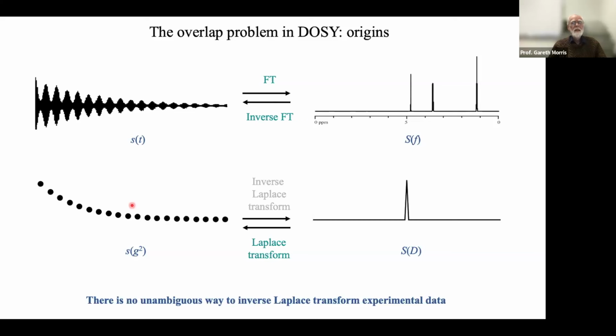And the snag is that there is no unambiguous way to do an inverse Laplace transform of data that are anything other than totally perfect. Electrical engineers do inverse Fourier transforms all the time with analytical functions that are very useful for determining filter characteristics and things. But if you take noisy experimental data, then it simply isn't possible to get a reliable inverse Laplace transform. Just to illustrate this, I'll show some distributions of signal on the right and the diffusional decay on the left. So we had a fairly sharp peak here, and we got what looks pretty much like an exponential decay.